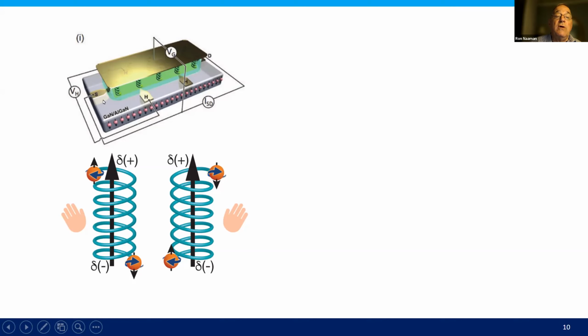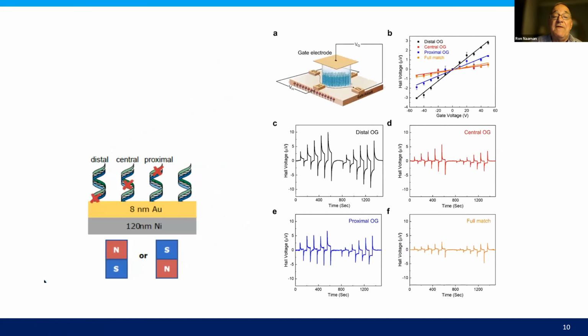In our case, we take the same Hall device, but we don't apply an external magnetic field. Instead, we adsorb molecules here on the surface. Everything here is done in solution, and we have a gate. The gate is insulated from the solution, so we apply a field on the gate, so it's an electrochemical gate, if you wish, and we see if we get any Hall signal. The first example is a case where we adsorbed DNA molecules on the surface. And here are DNA molecules that have damage in different positions.